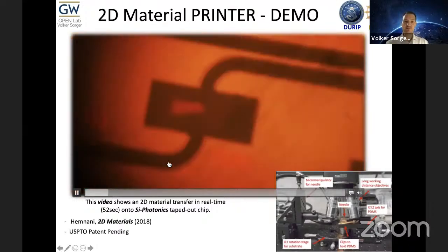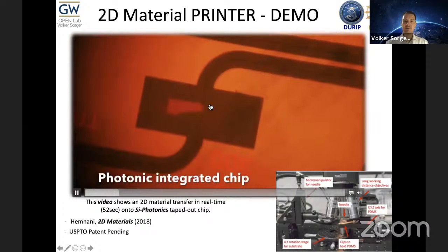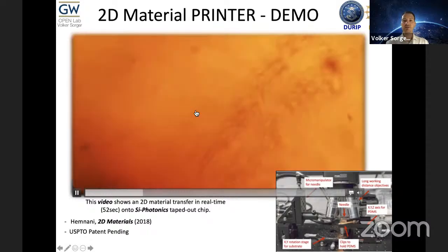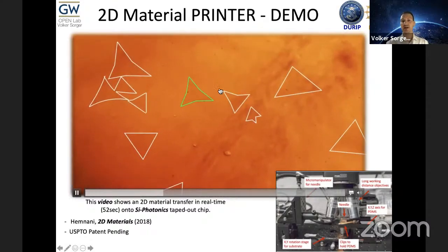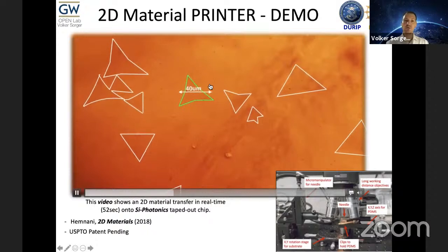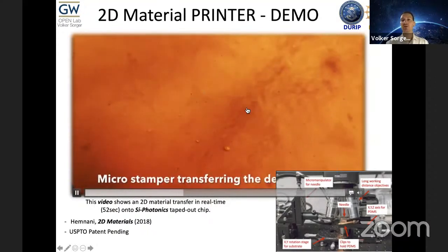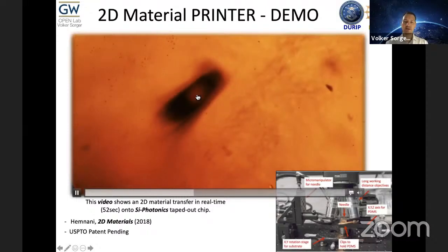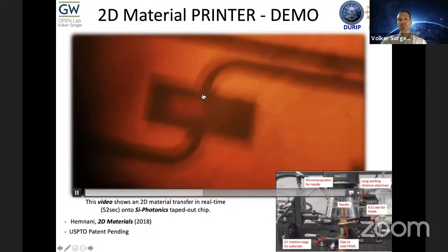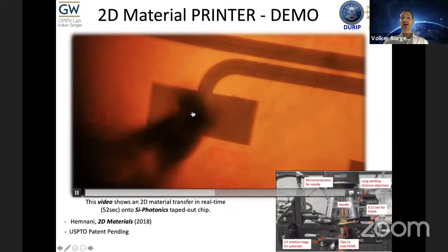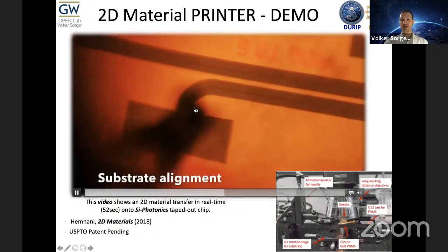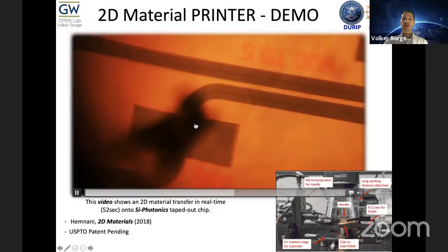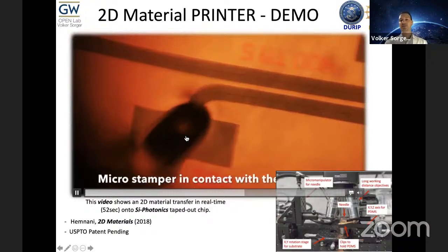So zooming down now to the chip. Here's a chip, and you see the photonic waveguide, and you see your pre-etched or pre-prepared contact right on this location where we transfer the material. We zoom up now to the PDMS on which the 2D materials are placed, and we want to transfer only this green flake and not all the other ones. So what we do, we take a microstamper, we align this microstamper with this 2D material and with the underlying contact structure, let's say of a waveguide. We press it down, we release it, and we can basically transfer this.